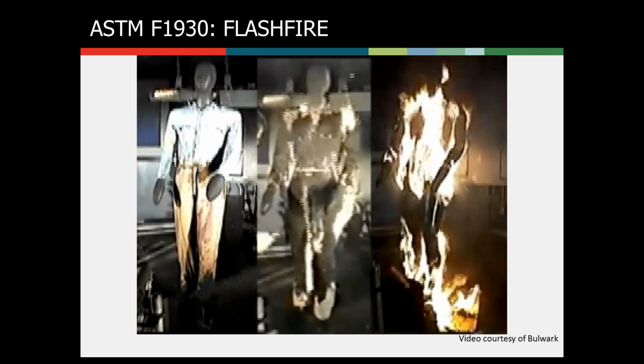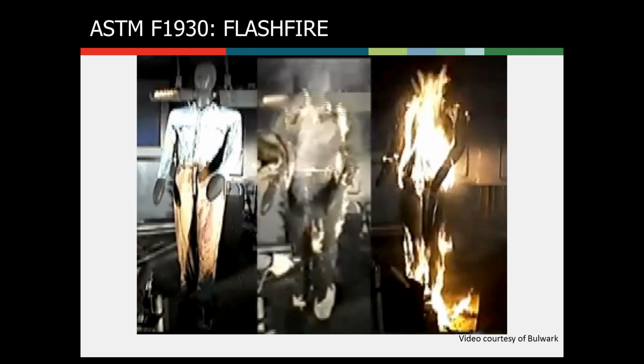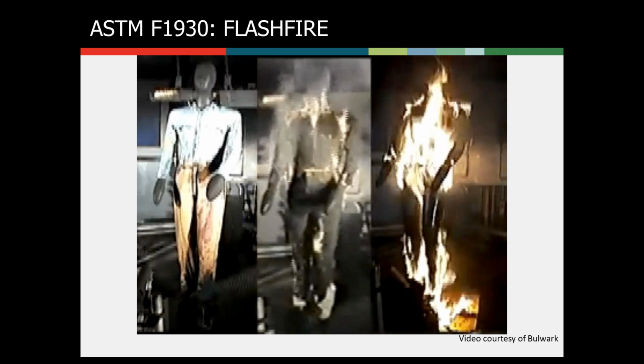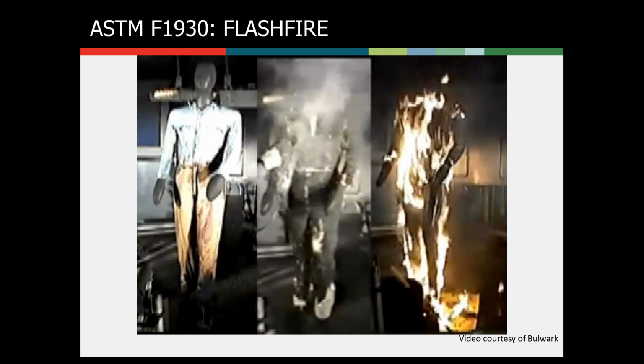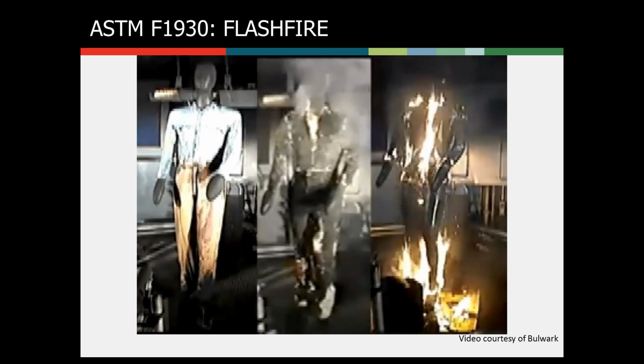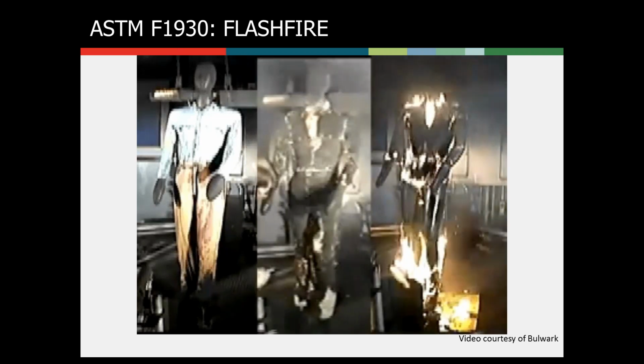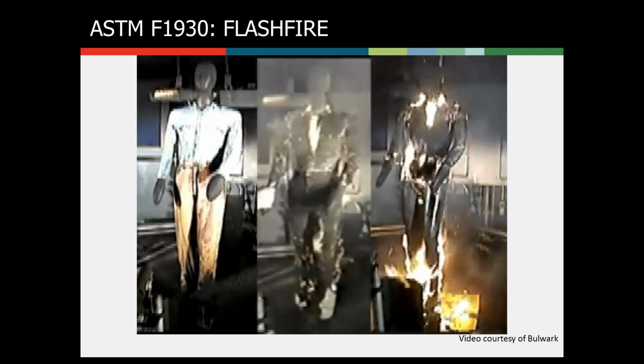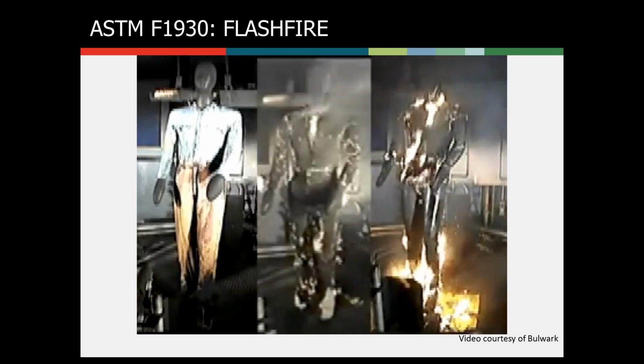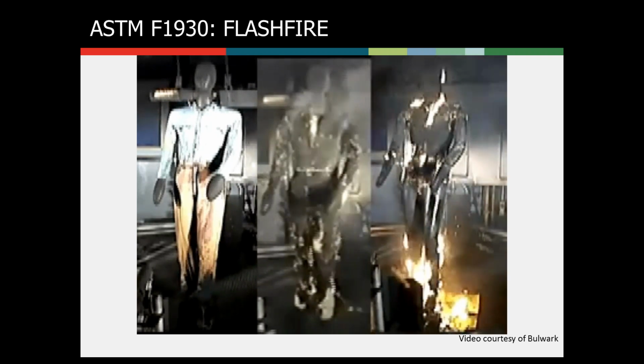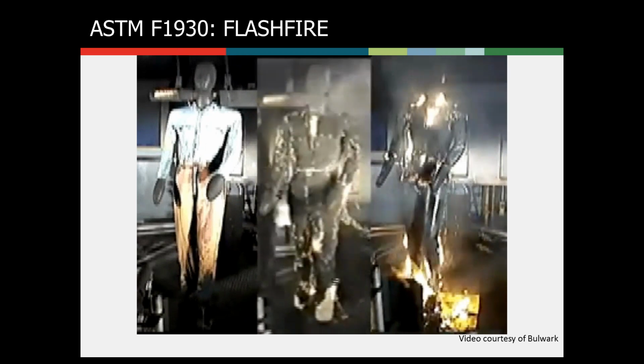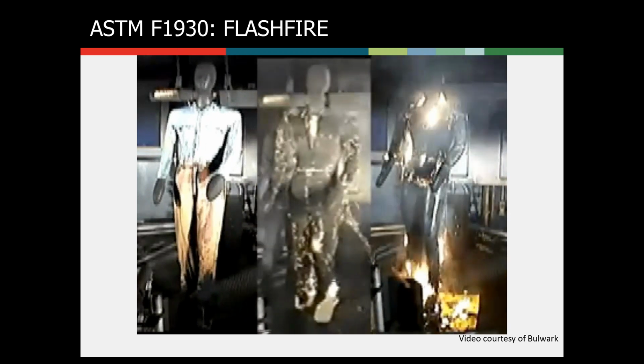Obviously, the ones in the middle and on the right, with the cotton and the polycotton, probably don't need to go to the data to determine you've got a fire hazard situation. The one on the left just has a little bit of char in a few spots, but for the most part hung in there pretty well from that exposure. Some different standards will refer to this ASTM F1930 test. For instance, NFPA 2112 requires that for your industrial garments, only 50% of your body would receive a burn after this test.